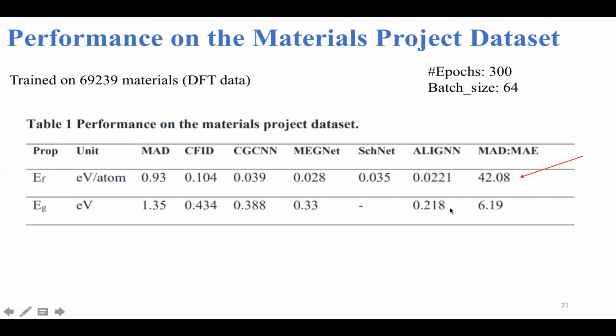There are two interesting things to notice here. First, the ratio of mean absolute deviation to mean absolute error is really high for classical quantities such as formation energy, but not too high for the band gap. Usually you want more than 5 MADs to MAE. We see that this is generally more than 5, of course, but for electronic band gaps, it's not in the order of 40s and so on. However, we notice that using angle information, we have decreased the MAE, mean absolute error, on the band gap model substantially. So this shows an interesting behavior, that actually including the material science knowledge, domain knowledge, in the deep learning is not too bad an idea.